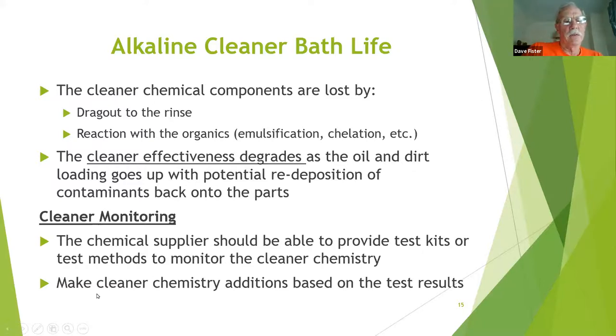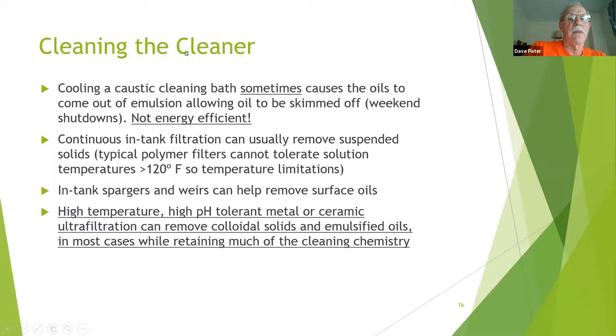So one of the things I've always recommended is make sure you're monitoring your cleaners. Most chemical cleaning suppliers can either provide test kits or have test methods to monitor the cleaning chemistry and to make the proper cleaning chemistry additions, so that there's always a way to keep the cleaning reasonably constant, at least in terms of the chemistry. Now, there are ways to get the cleaning chemistries cleaner, and I'll explain that. If you are doing a proper job of taking off your oils, they're probably being emulsified in the cleaning chemistry, or they're floating to the surface.